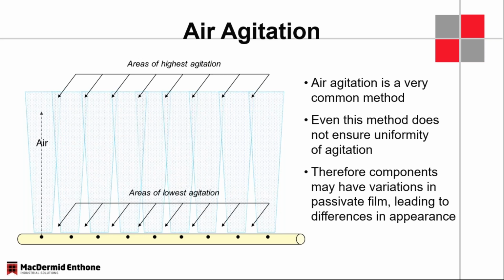So I had an applicator that had a 500-gallon tank, but it was longer and flatter. It wasn't that tall. I mean, it was probably only 4 feet tall. It was an automatic line. In a 90-second immersion time, we had the parts go down for 45 seconds, then go back up, and then back down for another 45 seconds. The reason for that was to get the bottom part of the rack through the upper part of the solution, where we had more aggressive air agitation.